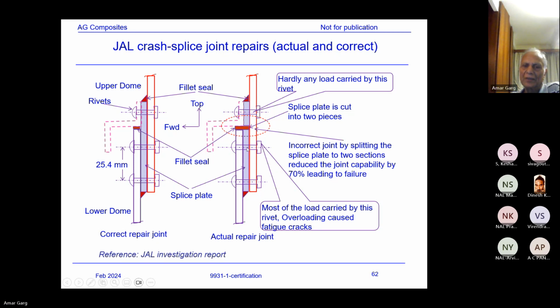And what happens, when the load is transferred, most of the load is carried by this rivet, which causes the cracking. So gradually the cracks propagated and final failure occurred due to that. So that means during maintenance, proper maintenance was not performed, it was not inspected properly, and that is why later on damage tolerance requirements came into the picture, that for every repair, damage tolerance considerations have to be given. The top rivet failure, accident happens.